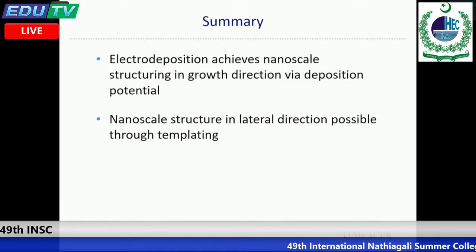And the second is, of course, that you can look at growth as it takes place, because you can do in situ atomic force microscopy for electrodeposition with a conventional AFM, but you're restricted to a growth rate of a fraction of a monolayer per second, sometimes even per minute. Whereas with the high-speed AFM, you get close to the speeds which are used in commercial electroplating.